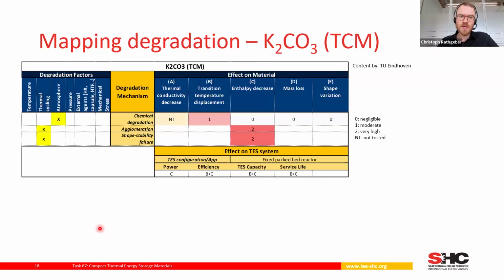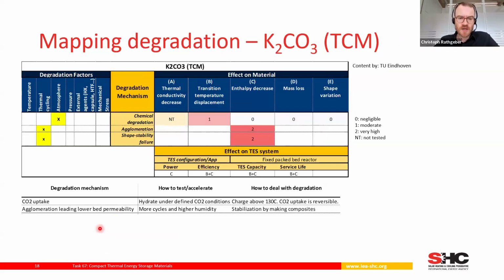A second example, a TCM, potassium carbonate. You see again the table, and well, these particles, we have seen pictures of TCM pellets and beads before. So one degradation mechanism is the agglomeration of the particles, and this is strongly correlated to thermal cycling as a degradation factor. So repeated heat and mass transfer to or from the potassium carbonate sample and particles leads to agglomeration.